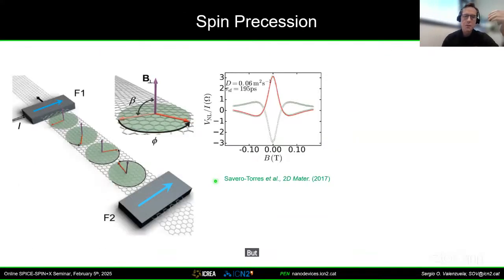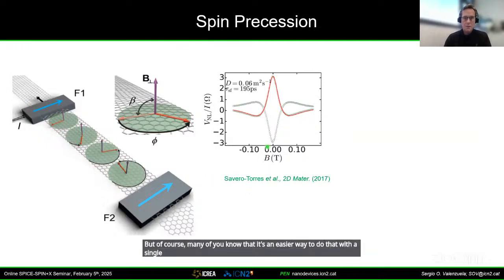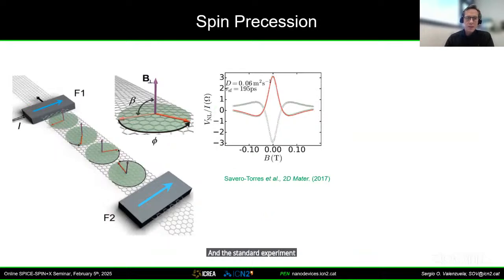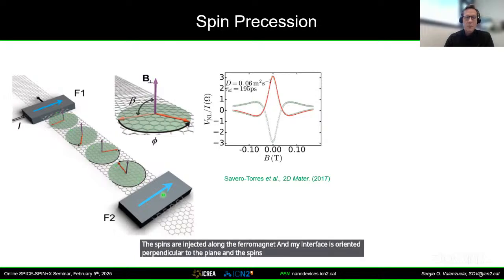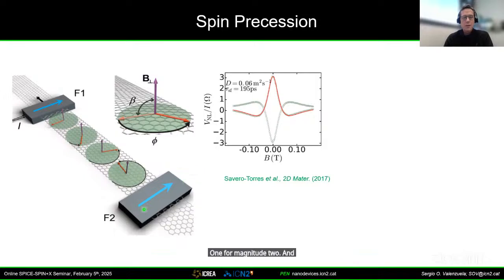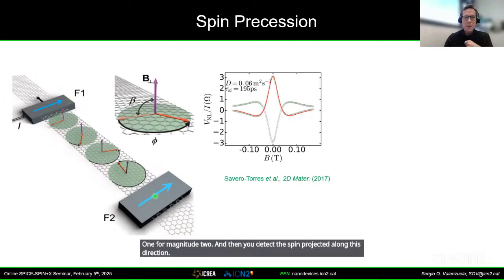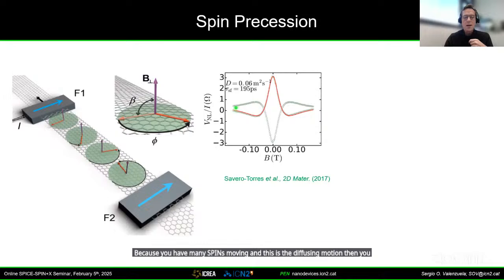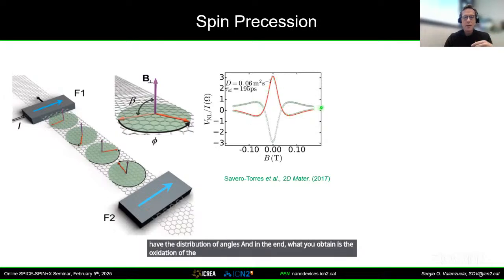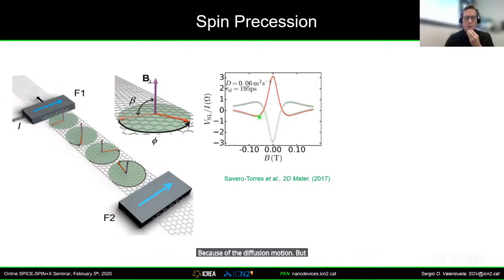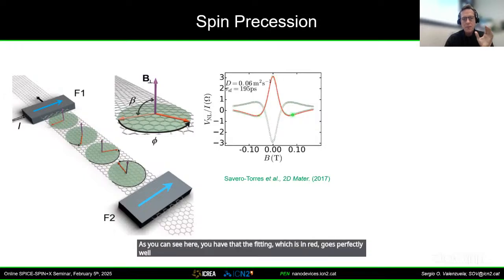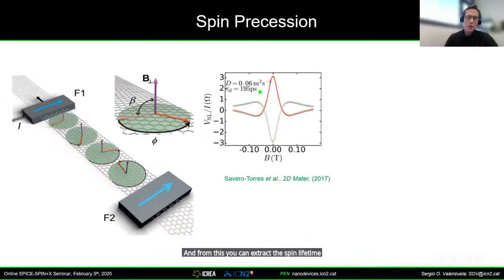But of course, many of you know that there's an easier way to do that with a single device, and that is by means of spin precession. The standard experiment for spin precession is represented here. The spins are injected along the ferromagnet. The magnetic field is oriented perpendicular to the plane, and the spins precess as they go from ferromagnet 1 to ferromagnet 2. Then you detect the spin projected along this direction. Because you have many spins moving, and this is diffusive motion, you have a distribution of angles. In the end, what you obtain is an oscillation of the signal that dies away for large enough magnetic field, where you have 360 degrees covered because of the diffusive motion. But we know very well how this behaves. As you can see here, the fitting, in red, goes perfectly well with the data, which is underneath in green dots. And from this, you can extract the spin lifetime and the diffusion constant of the spins.